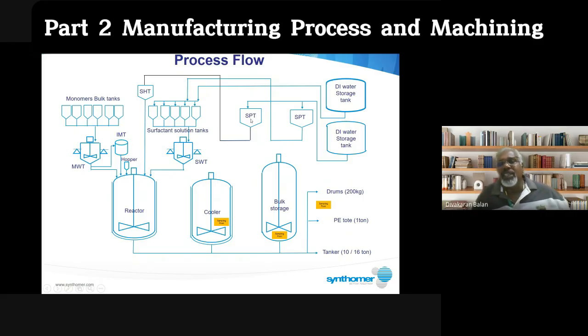And this SPT here is normally for colloid PVA solution preparation. But PVA solution is just for certain products. It's for vinyl acetate products. For acrylic products, there's no PVA solution. We just use water. The water we use is deionized water. Here, deionized water.